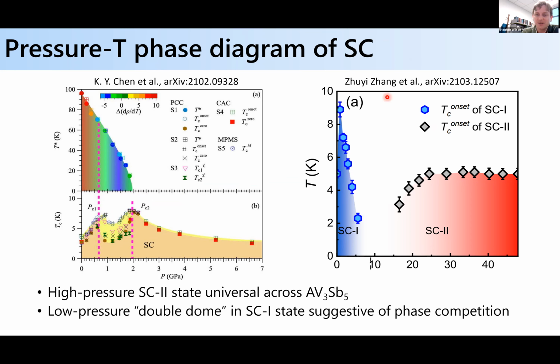Again, in the cesium system, similar to the potassium system and also the rubidium system, as you look at even higher pressures, right? So this ends at 7, right? If I now pick up here, TC recovers and has again a higher temperature, higher pressure superconducting phase, which might be distinct from the low pressure one.